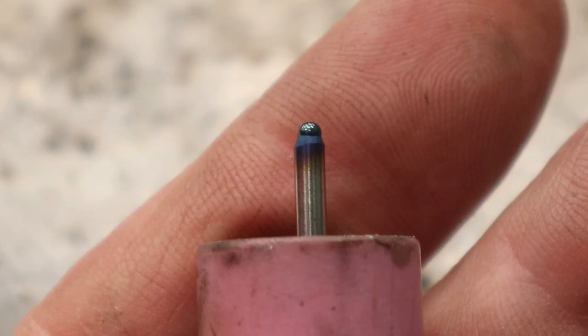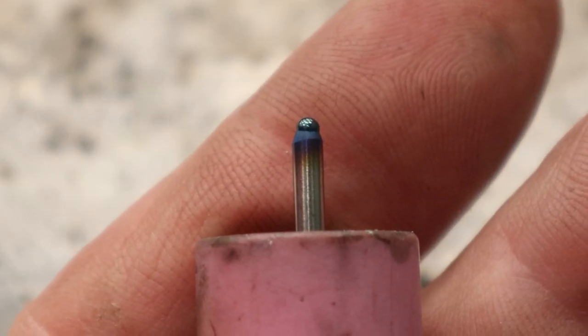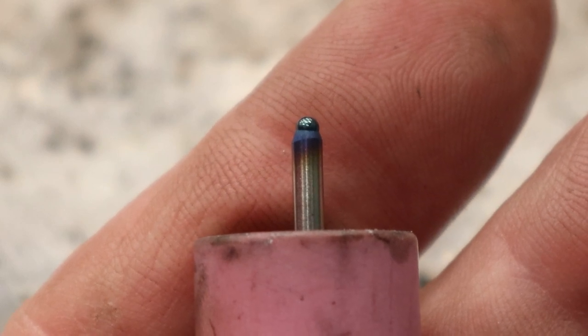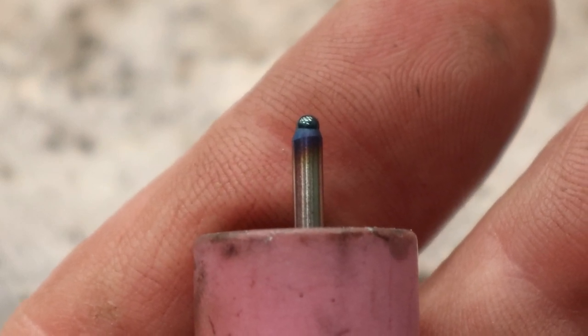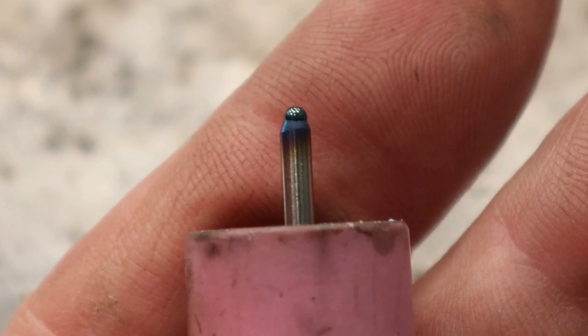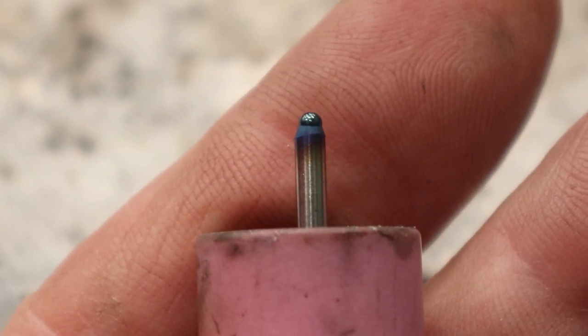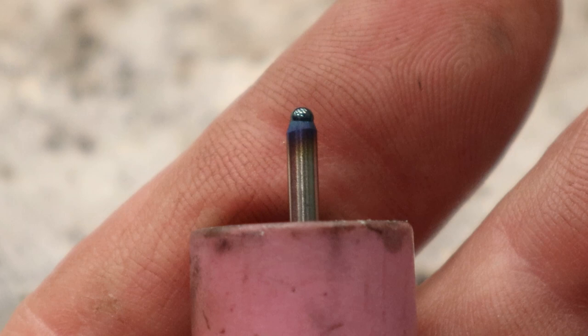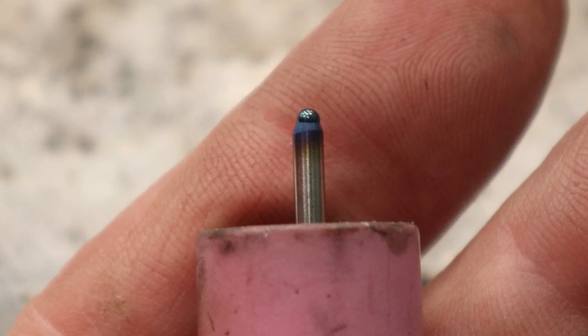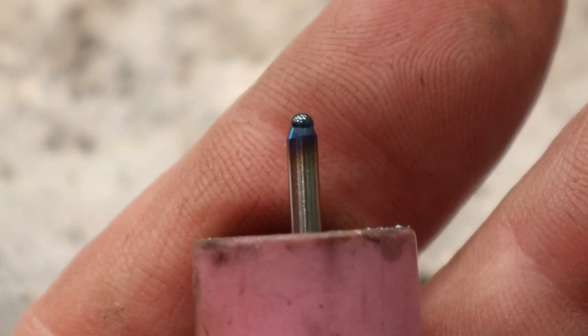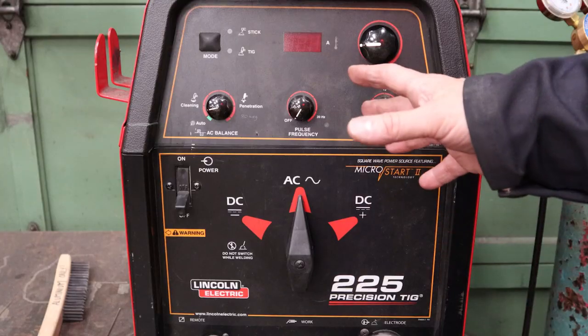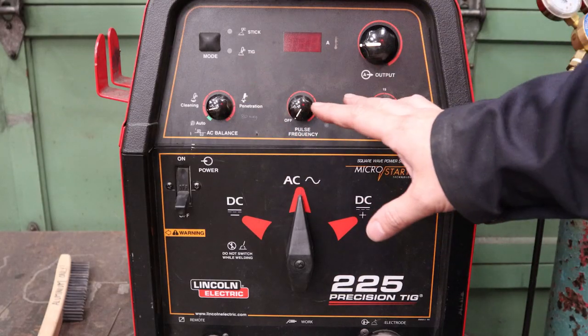With the quick method on DC positive, I turned the amps down to about 45, 50 amps so that it wouldn't just disintegrate on me. And it took a couple seconds. And you can see I did not make a ball the size of the diameter. I find that I get a little bit better control and a tighter arc cone if I leave some of the taper there. Now, if you've got a machine that has balance control, it's really quite easy.